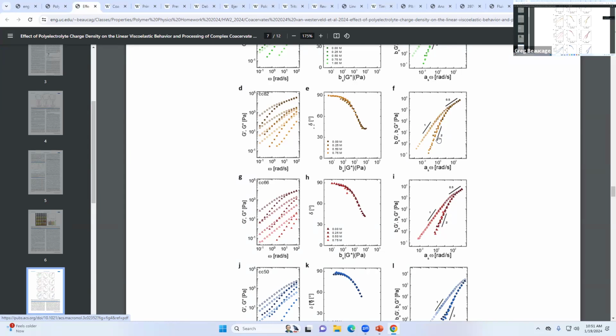Right, that's the reason you always, so this is Newtonian flow. Basically, that's low viscosity, not this viscoelastic flow at low shear rate. So you have power laws of the storage and loss modulus go 1 and 2. Then you have the crossover point here, which would normally be the time scale of the system. So normally you expect the storage to go above the loss there and then plateau out, and the loss would drop. And then you'd have a plateau modulus, which would be the modulus of chains that are entangled at the entangled points, and that makes a rubber. So that's the modulus of a rubber that has chains that are entangled. On the time scale the entanglements can't relax, then it turns into a rubber. So you'd have a plateau of the G prime, and G double prime would drop.